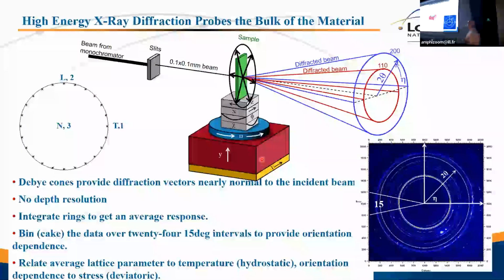We've gone through most of this. So when you collect the data, this is what the 2D diffraction image looks like on the GE detectors at 1ID. You guys have seen lots of stuff that looks like this. We analyze the data in two different ways, again, because we're going to try to deconvolute the effect of temperature from stress. Now we're lucky, this is, I don't think I said it, the material was 316L stainless steel. I'm sorry, that's wrong. It was 308 stainless steel, which is what you tend to use to weld 304, because it has higher chrome. Sorry, you didn't need to know that.